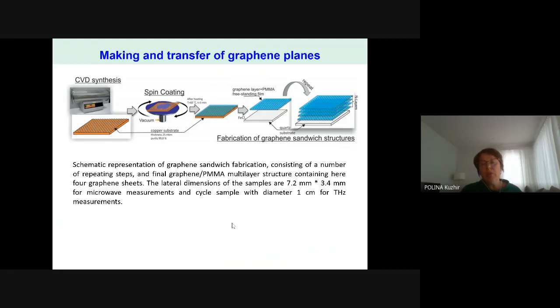But what is not very good is that for handling this graphene, for transferring it, you normally use different layers of thin polymers, and if you need a number of graphene layers stacked into sandwiches, you will need this thin layer of polymer every time. But what is good about our application, if we speak about microwave and terahertz frequency ranges, is that this 100 nanometers of polymer is invisible to electromagnetic radiation at these frequencies, because 1 terahertz corresponds to a 300 micron wavelength, and 30 gigahertz corresponds to 1 centimeter.